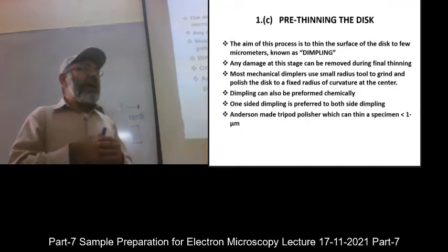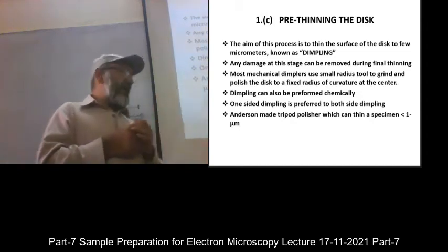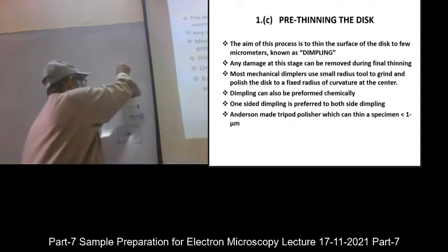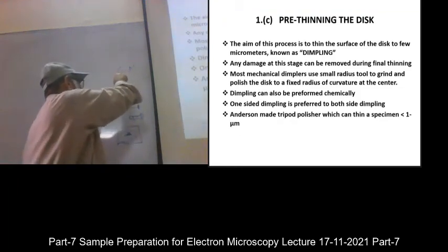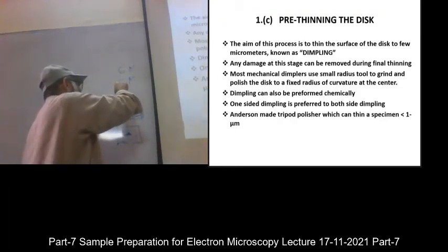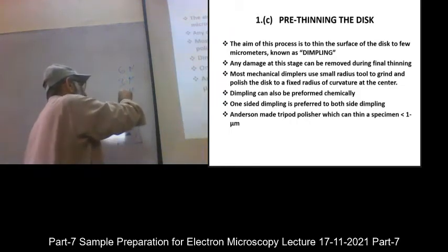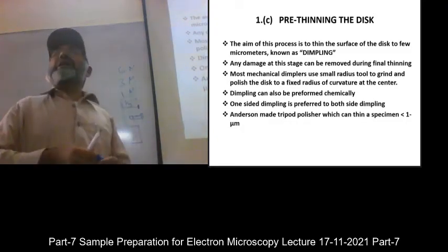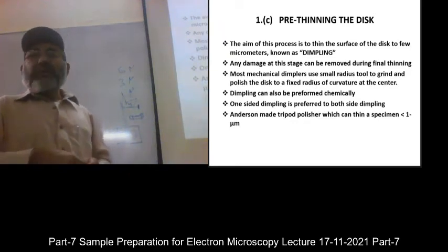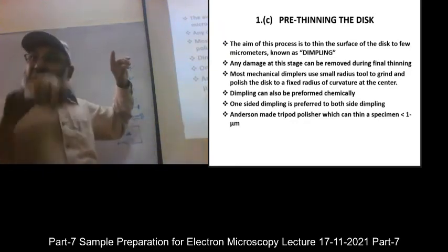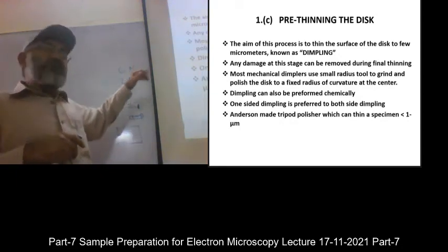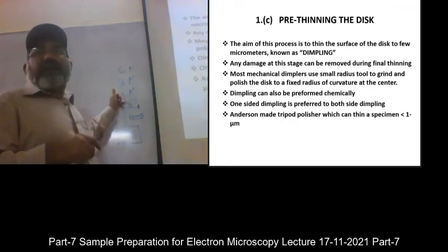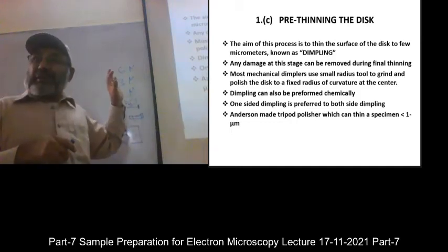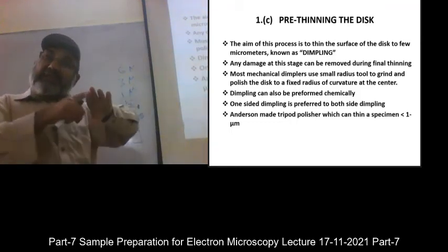Because if you are using 6 micron, 3 micron, 1 micron, a quarter micron, there may be half or different. So this quarter micron is only polishing the sample, but the other ones are grinding the sample. So for example, if you use quarter micron, it only polishes the sample, shines it, but it doesn't